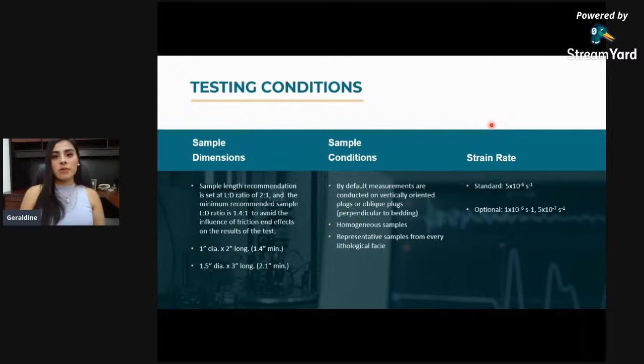The strain rate. As a standard, we use 5 × 10 to the -6 strain per second, but optionally, for unconventional reservoirs where you have very, very low permeability, you can also use other strain rates.